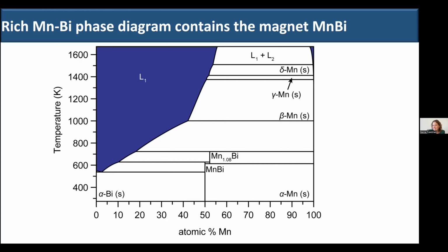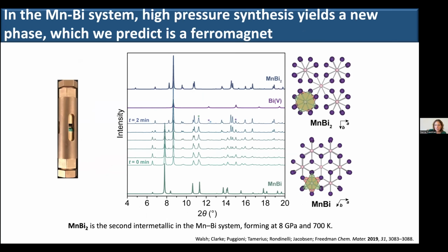So we decided to continue exploring the manganese bismuth system to see if we could identify any other compounds that might shed light on the magnetism that bismuth can induce in a system. So in doing that, we created a new binary compound, MnBi2, that we accessed at high pressure, as shown here, at 8 GPa and 700 Kelvin.